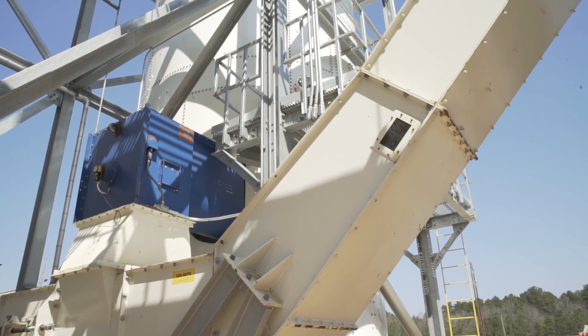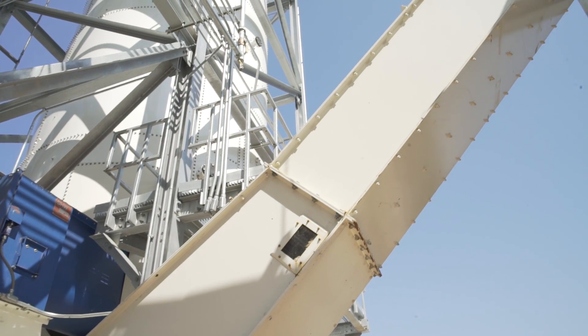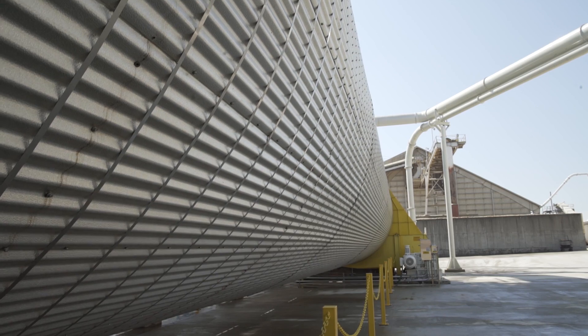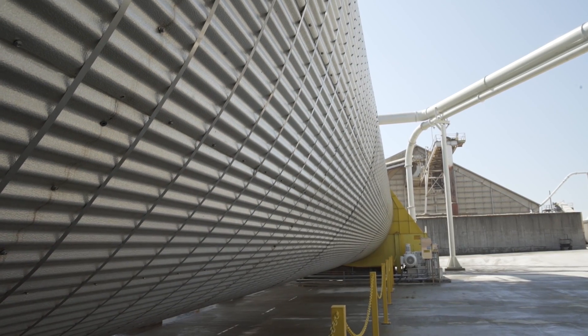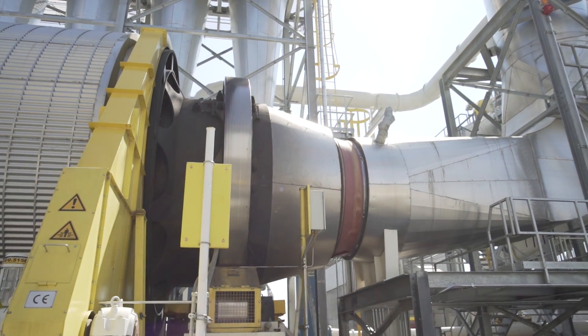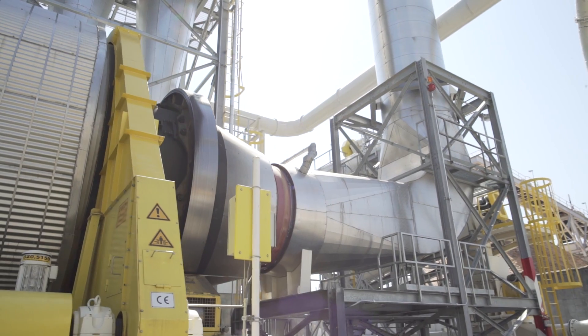The material is sent to the drying pad. Here, large drying units reduce and balance the moisture. Wood chips with a moisture content of 40–50% and shavings with 15–20% are dried to 2–3% for core material and 6–7% moisture content for surface material.